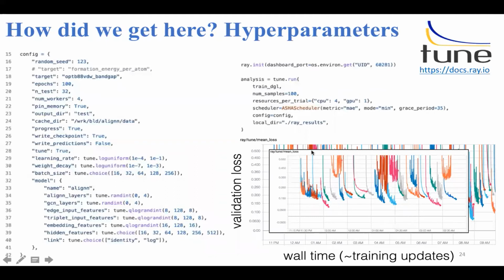It was a long, tedious process to get the hyperparameters. So we first tried a bunch of parameters in the ALIGNN model. Then we did use Ray Tune to get the final parameters. Some interesting thing we noticed is that we had to use something like a one-cycle scheduler and SiLU kind of activation function, which is slightly different from other graph neural network models. And we also use the DGL framework, which makes our model really, really faster compared to others.